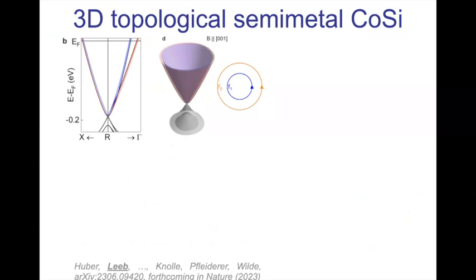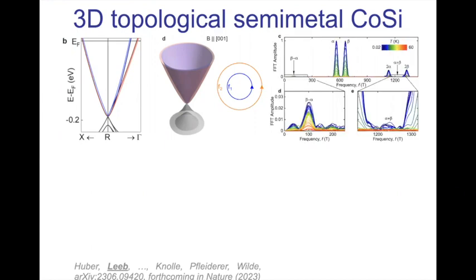And that's also the reason it's a very nice example to study first. Due to symmetry, there's only 2 allowed orbits around the R point, which will give you quantum oscillation frequencies. So these are the main features in your spectrum. It's alpha and beta frequency.